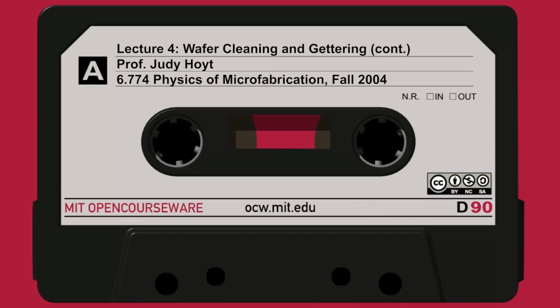This is kind of an old-fashioned technique. People used to use it because alkali ions tend to be trapped in that glass. It's not so much in use anymore because it tends to absorb water later on in the process. And if you are using aluminum metallization, that can cause corrosion. So the approach to alkali ions these days, as opposed to trying to getter them, is a little different. People just try not to get them in during the process. And then once the chip is fabbed, they don't want them to get in after fabrication. They put a protective layer.